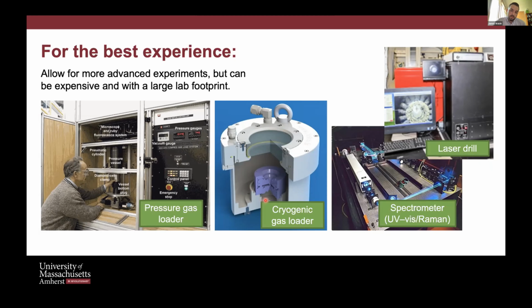A less hazardous and more accessible way of doing gas loading would be with the cryogenic gas loader. So in this case, you're using a liquid nitrogen bath to condense a gas. And so really this only works with gases that will condense below 77 Kelvin. So argon is typically used in this way. And so there's no high pressure involved. You're just using very low temperature to condense your gas into a liquid, which then goes into the sample space. So this gives you access to really the best hydrostatic pressure transmitting media.